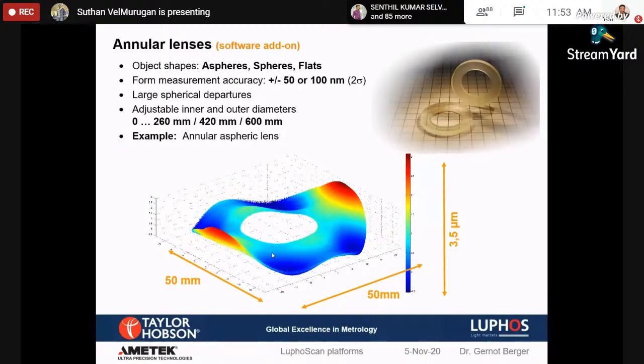The annular lenses have a few limitations on the contact profiler because there is a hole in the middle and the thickness of the sample is very small, like 1 millimeter or 2 millimeter. It's very filmy. Because the contact is going to touch, we should have a proper vacuum chuck. But in non-contact, nothing is going to touch, so there is no force acting on the sample. So it is always preferable for the filmy sample on the non-contact principle.